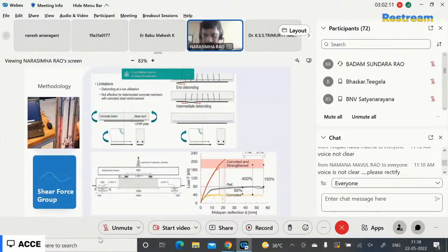Once we compare this beam specimen's moment elevation relationship with the FRP strengthening system's improvement, there is an increase of 400%. That concludes that the FRP system has much more advantage and efficacy in improving the load carrying capacity, that is the moment of resistance. Almost 150% can be improved with respect to the original uncorroded beam specimen, and an increase of 400% can be attributed when compared to a specimen with the 50% or 20% corrosion that was there in the steel reinforcement of the beam.